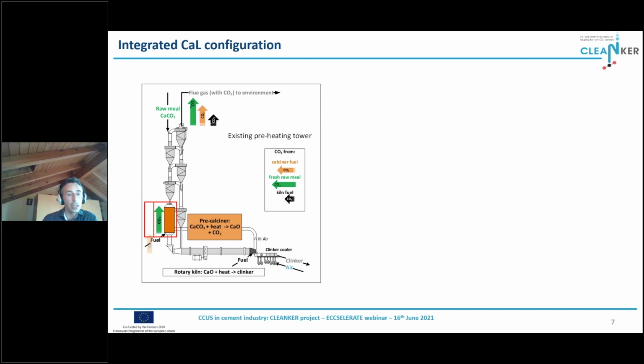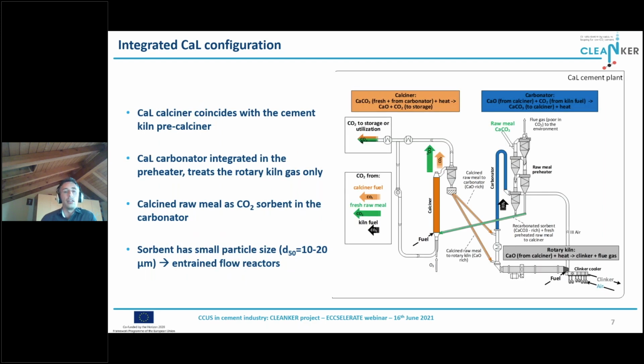Still in the precalciner, we have also another arrow, the orange one, which is the CO2 generated from combustion within the precalciner, which is needed to sustain the calcination. Then we have a second contribution from combustion, the minor one, generated by the main burner in the rotary kiln. This burner is needed to bring the raw material to very high temperature and to produce clinker.